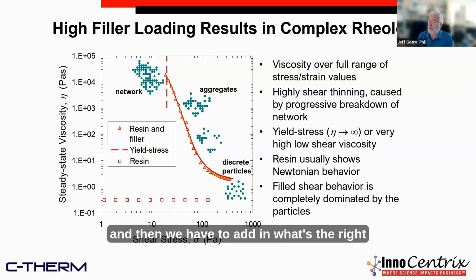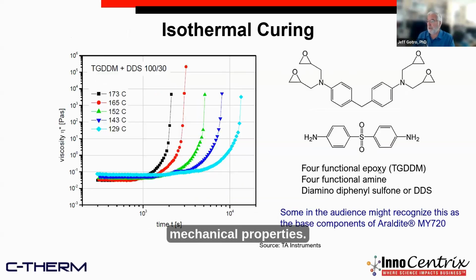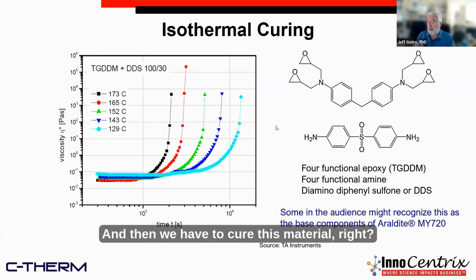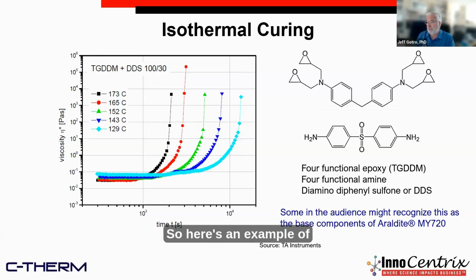And then we have to add in the right filler for thermal conductivity or coefficient of thermal expansion, and then electrical properties and mechanical properties. And then we have to cure this material, right? So here's an example of an epoxy that has these epoxy rings on it, and these have an amine group on each end, right? And this amine reacts with this epoxy to open the ring and polymerize.